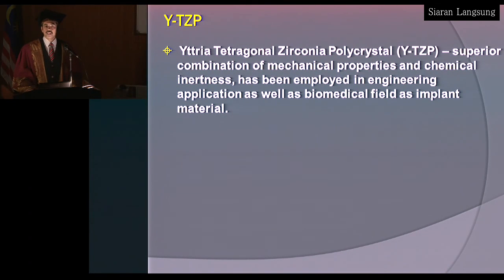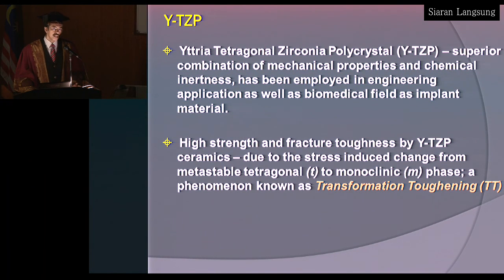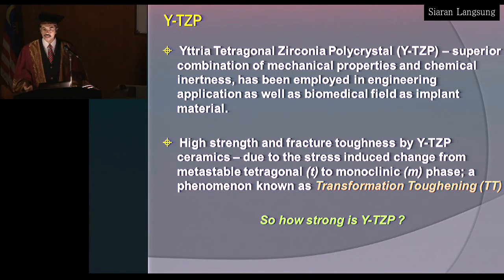Okay, when we look at the Y-TZP material, it has exceptional strength and toughness, mainly because of its tetragonal structure. And it has been used in many applications, in biomedical fields, in dentistry, in mechanical engineering fields. Now, why is the tetragonal structure important to zirconia? Zirconia exhibits a very peculiar behavior known as transformation toughening. Now, this is a self-healing mechanism. So what happens is that when the material is in the tetragonal structure, it responds to stress. When there's an external applied stress, like in the form of a crack trying to propagate through the structure, the material tends to absorb this stress, okay, and results in transformation.